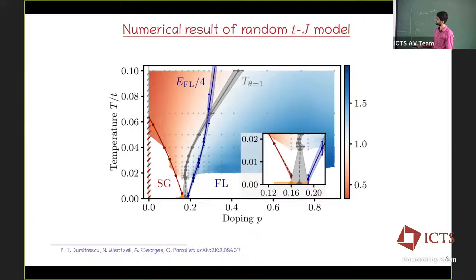On the lower side, you have some spin glass. On the right-hand side, overdoped side, they do call it a Fermi-Liquid. But you see that the exponent is varying continuously as a function of doping. So it's only in the limit where you go to very, very high doping, you start seeing the dark blue color where it actually approaches the value 2. But anywhere in between, it's really a non-Fermi-Liquid kind of behavior.